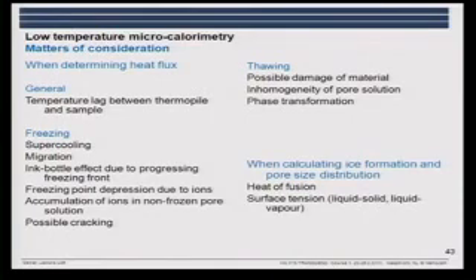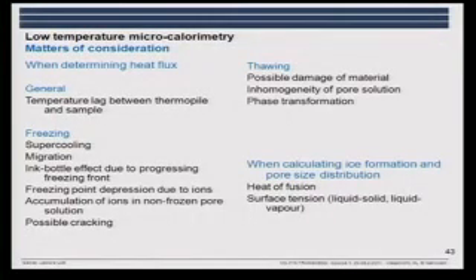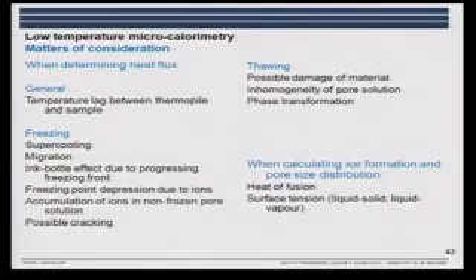We have to consider the ink bottle effect, which is not considered in all literature if you go back. We have the freezing point depression due to the ions, and when the freezing takes place, you have a brine being made. So the water is freezing, but the ions are being left in a part of the solution which is getting more and more concentrated. So we have this accumulation of ions in non-frozen pore solution, and then there might be possible cracking. So you see, it's not perfect. Then thawing, possible damage of the material, inhomogeneity of the pore solution, which we get, and we have the phase change transformation.